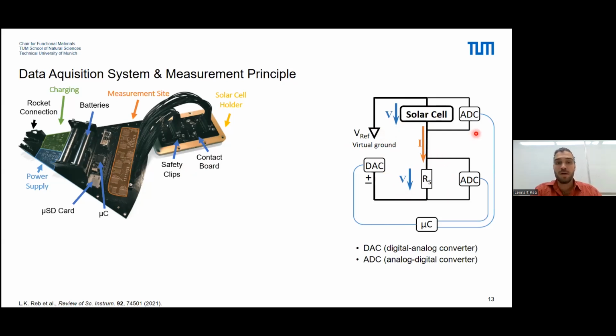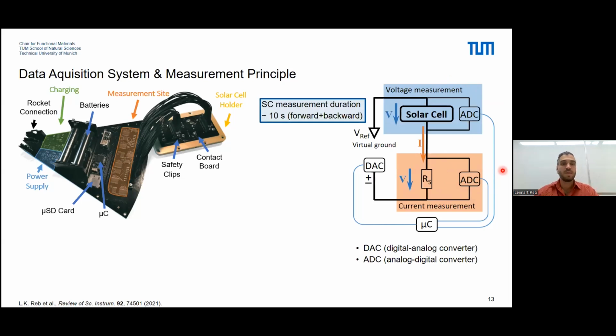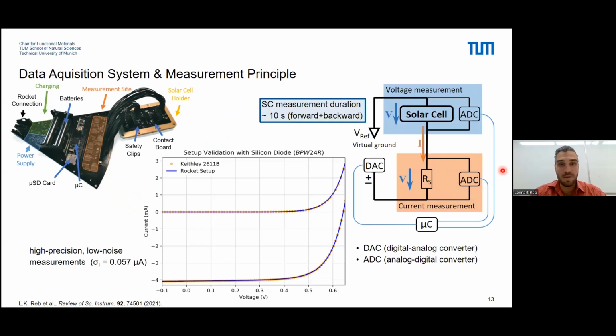What we can do now is use ADCs, analog digital converters, that measure voltages. By measuring the voltage drop across the solar cell, we know the voltage of the solar cell. We can similarly measure the current via the voltage drop across this resistor and convert it via Ohm's law. One solar cell measurement in total, including forward and backward sweep, took around 10 seconds. And of course, we tested the quality of these measurements. For this, we used a stable silicon photodiode and compared our rocket setup with the Keithley laboratory setup. We found no real difference for the dark and for the illuminated measurements, individually. So we have high quality measurements.